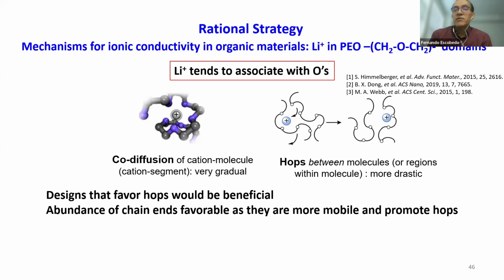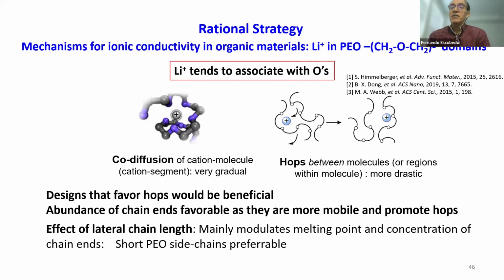In that context, the abundance of chain ends would be favorable because they are more mobile than segments which are inside the molecules. They will also promote hops, because if you go from one chain end to another chain end, that will make it more effective. That tells you what the effect of the lateral chain length is. Besides modulating the melting point of the material, which defines the range of temperatures where the material can be worked on, since they don't want to be operating, say, above 100 degrees Celsius or below room temperature, more importantly it controls the concentration of chain ends. So it would be preferable to have a system with short PEO side chains. And in fact, that's exactly what we had in this liquid crystal that I showed you before, with thiophene and this PEO material.